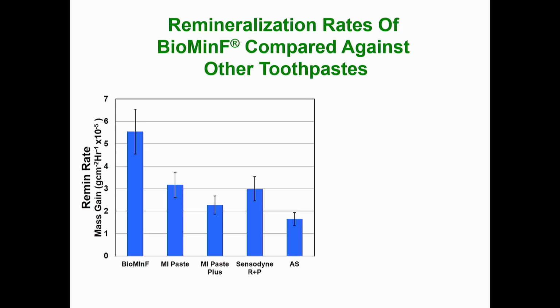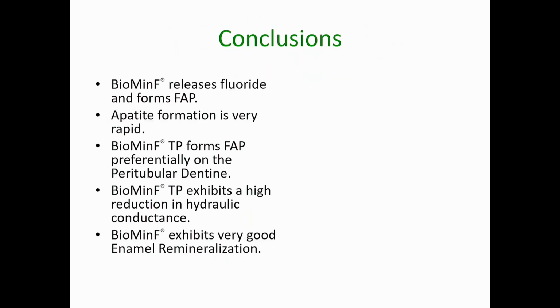And then we have MI Paste Plus and MI Paste, which you may know in China as Tooth Mousse and Tooth Mousse Plus, which is an amorphous calcium phosphate, which also does quite well. But if you look at the Biomin F, it is almost twice what the commercial products are, and about 3 times what artificial saliva is. So you can see the Biomin F has a very high remineralization rate.